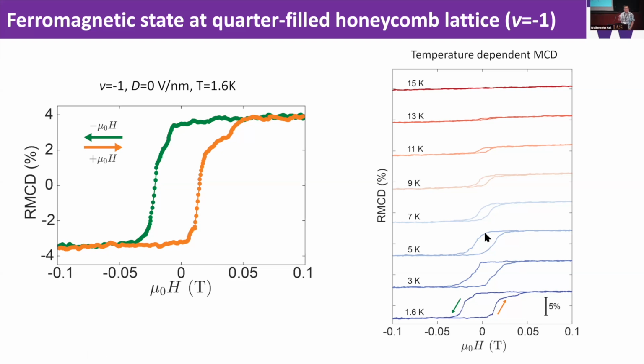You may think, 14 Kelvin is low temperature, way below room temperature. But I want to emphasize 14 Kelvin actually is a high temperature for 2D magnetism. First, it's a two-dimensional system. We know that in the two-dimensional limit, magnetism usually has a really low Curie temperature.